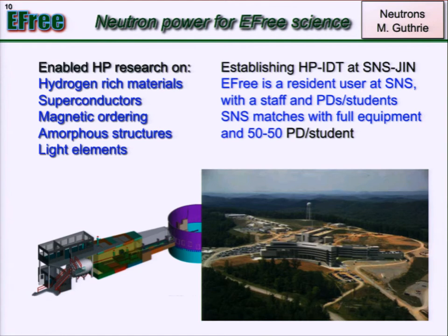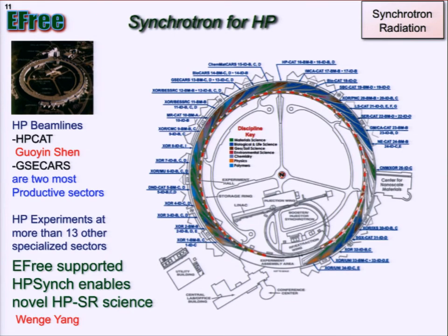Also, we use the new neutron source, the spallation neutron source at Oak Ridge. We use the synchrotron source. The synchrotron is currently more than half of our activity, because synchrotron X-ray has already developed many different special methods to study almost the whole textbook of solid state physics, from structure to electron property, phonon property, the ferroelectric property. So for all those, you have some synchrotron probe developed.